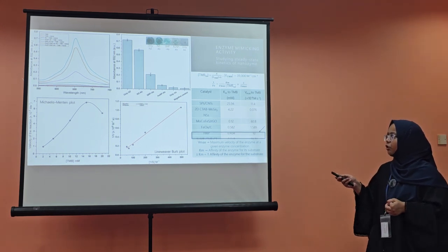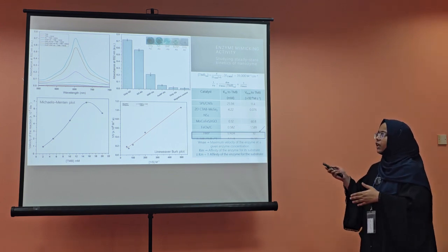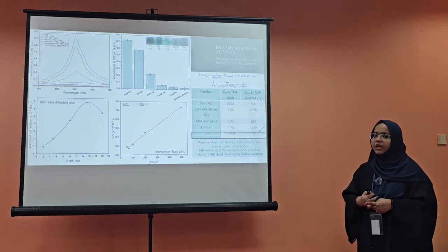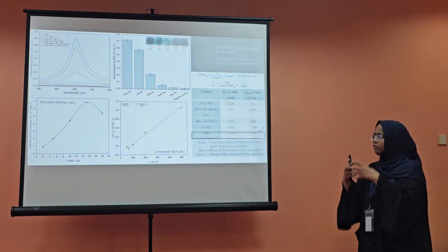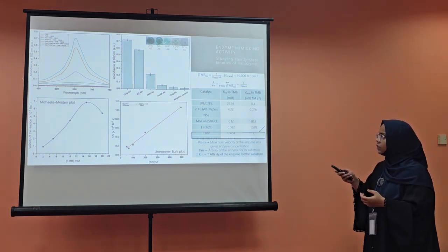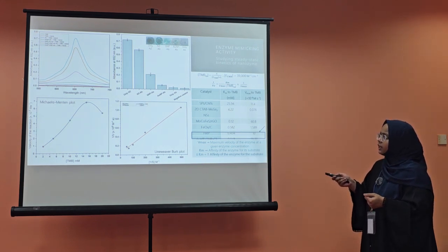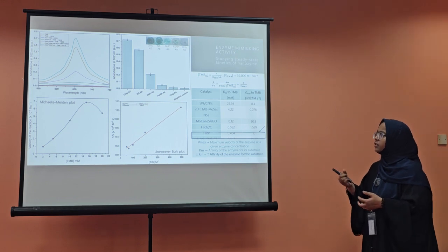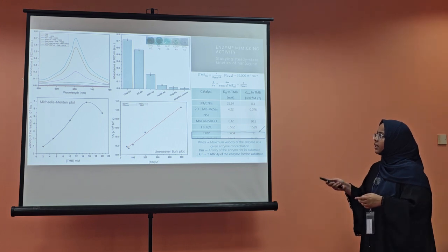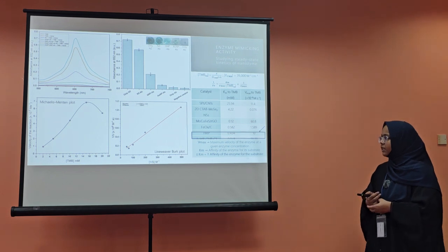Upon conjugation with the antibody, the absorbance decreased slightly, even though the color changes were significant enough to carry out further experiments. The slight decrease suggests that the antibody covered the surface of the nanozyme, and certain enzyme active sites were covered. That's why there's slightly reduced peroxidase-mimicking activity. However, graphene nanoplatelets on their own or gold nanoparticles on their own did not give significant absorbance, suggesting that this developed hybrid nanozyme had the maximum enzyme-mimicking properties.